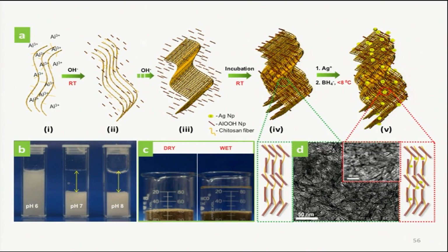So what we did was that we have biopolymers, and these biopolymers, which are soluble in water, were converted to stable materials which have Young's modulus equivalent to silica or sand outside. And these have structures like these, sheets about 50 nanometers thin, and you can pack these sheets like that with biopolymers, interlocking them, creating cages. And in these cages, you can put nanoparticles. And such nanoparticles, very interestingly, you can put water through it. Water will go in, nanoparticles will leach out something, these ions can come out into water, and they can be used for disinfection. And these nanoparticle surfaces will not be coated with contaminants present in water, because those contaminants will not get into these cages. So this is quite interesting.